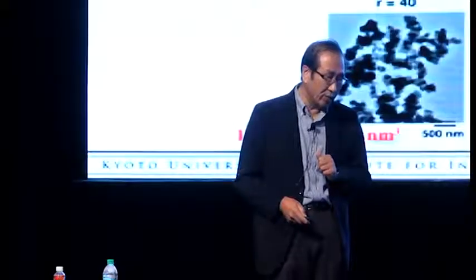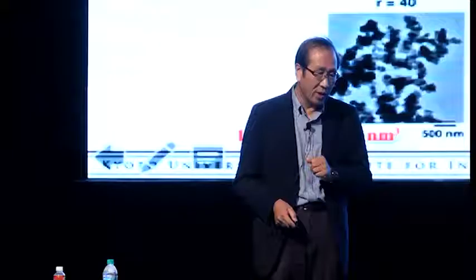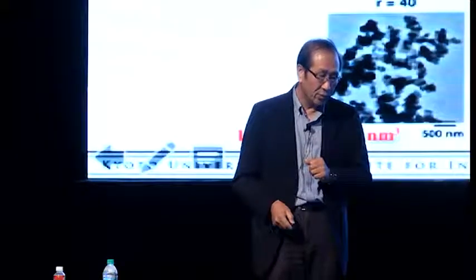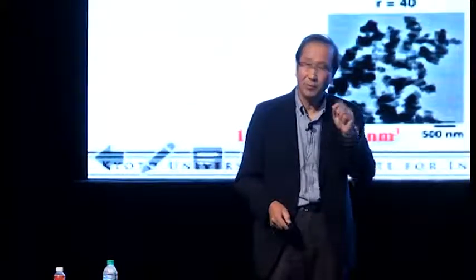So this is crystal. The size is 45, 60, 110, 160, 300, 500 nanometer. We synthesize different sizes of the crystals. So we observed what happens with full loading and after removing gas molecules. This is just the results. In the bulk phase, large crystals, once we remove the gas molecule, the structure collapses like this. This is the closed form. But in a certain size of crystals, for instance 60 nanometer, you see this open form is maintained even without the gas molecule. And then by heating, by giving a stimulus, the structure converted to the closed form.